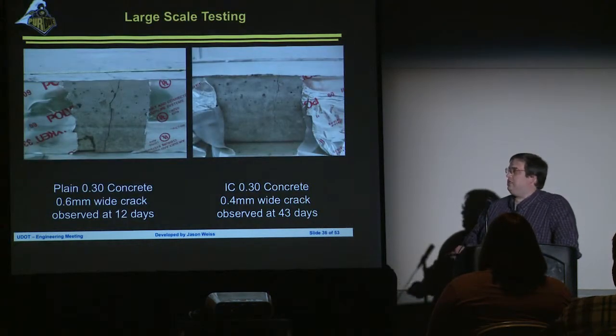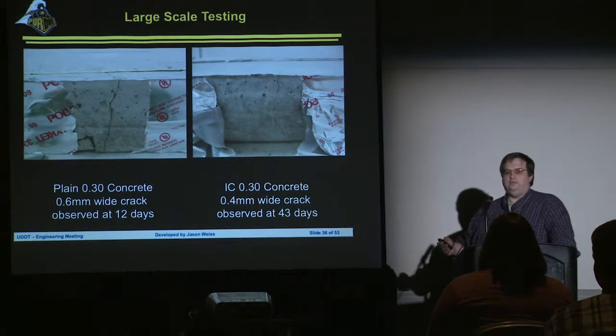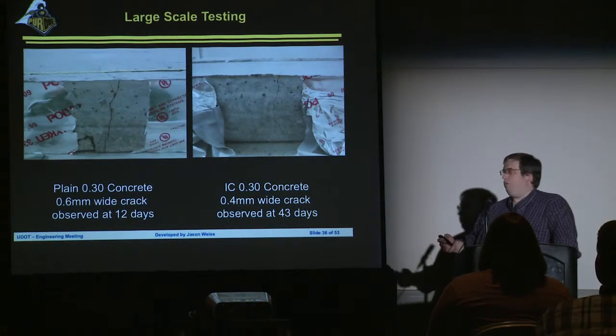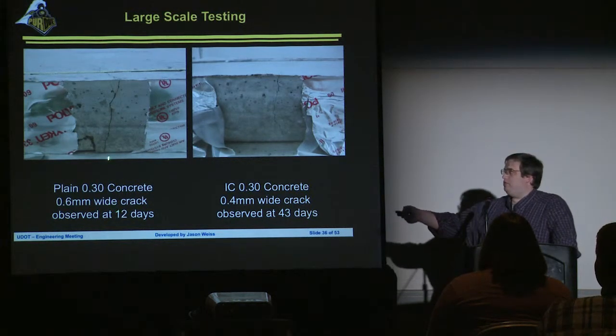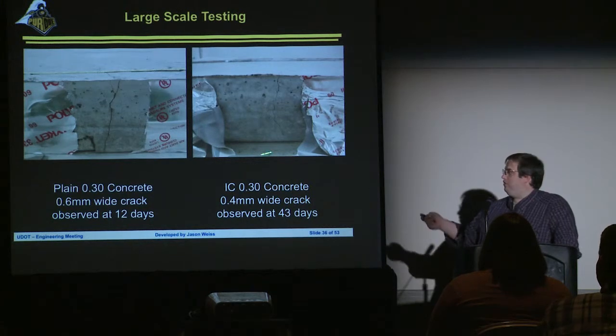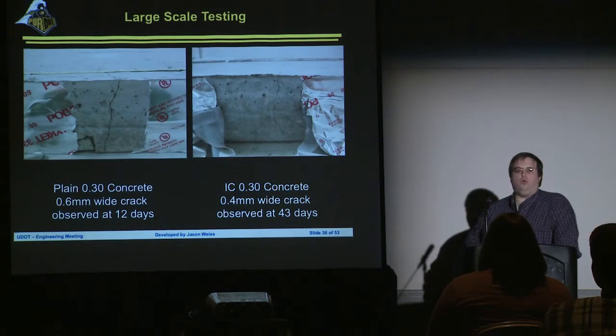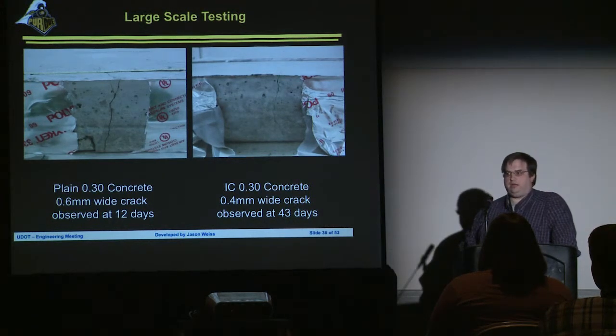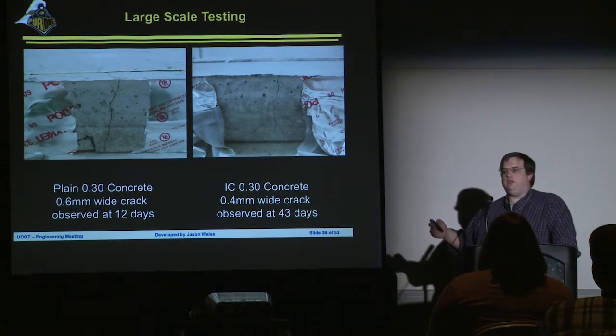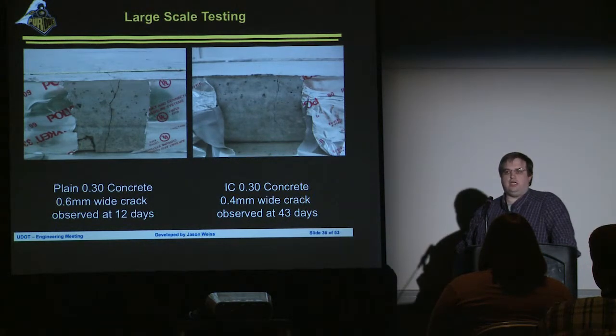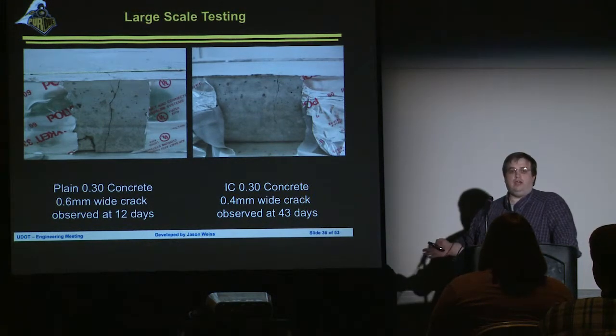And what we see is that at 50% humidity, a 30-mile-an-hour wind, for 12 days, we see a 0.3 system started to crack. With internal curing, we had to go out to 43 days to get this system to crack. If you've got a bridge deck that's exposed to 50% humidity and 30-mile-an-hour winds for 43 days with nobody doing anything to protect it, you're going to have a system that's pretty durable here.